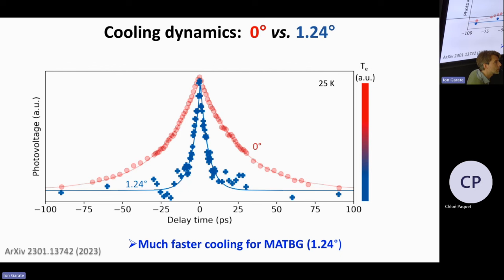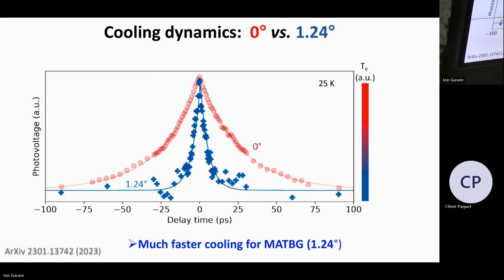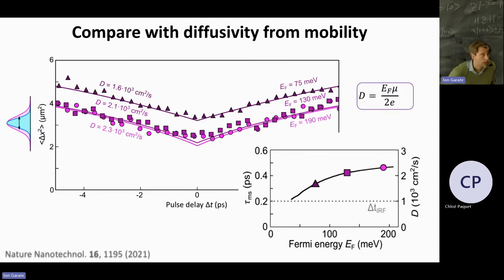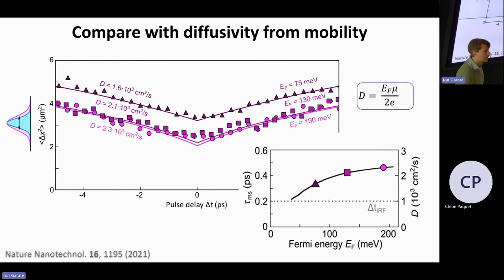Yeah. And you verified the Einstein relation between diffusivity and mobility, the other part of the talk, right? Yeah. Was there any reason to expect it wouldn't work? We were aware of the hydrodynamic work from Columbia University, so we knew that there would be a chance of breaking the Wiedemann-Franz law. We weren't sure if that was going to happen at room temperature, because, of course, their work was at a few tens of kelvins and extremely clean devices, like two or three orders of magnitude lower charge puddles than what we have. But we just tried, and then we saw this and we thought, okay, that could indeed be this breaking of the Wiedemann-Franz law.